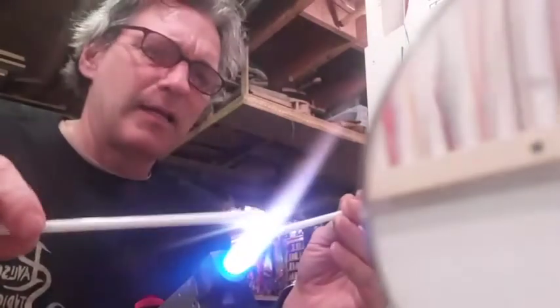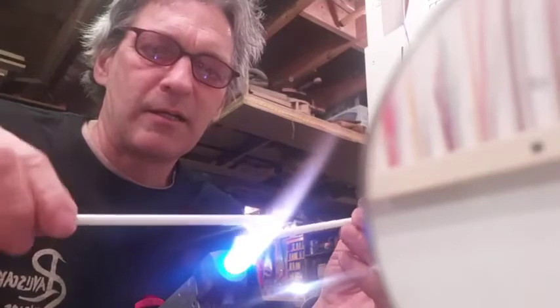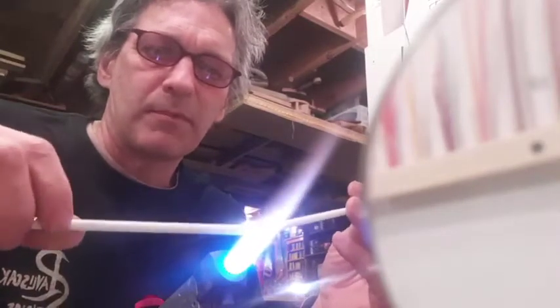White is a shocky color, so I'm going to flash these rods a little bit, meaning I'm going to wave them through the fire till their temperature rises a little bit. If I just stuck them right in there, it would crack, and I might never start getting our gather on, and they would just keep cracking off. Very annoying. So now you can see they're starting to melt. White turns clear when it begins to melt. Transparent.